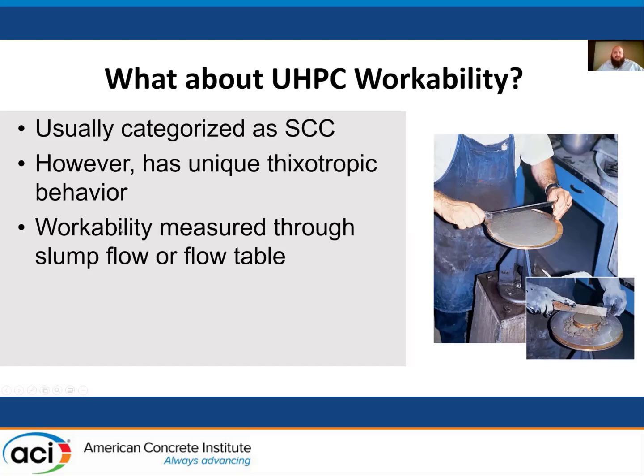But a lot of times with the workability, people use a slump flow. If you're not familiar with that, they invert a slump cone, and then they'll pull it up and measure the spread. Or they'll use the flow table, like you see over here on the right.